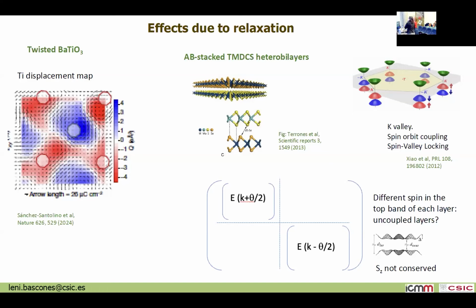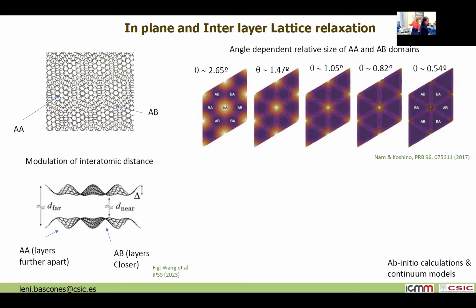G-Dye says, will the interlayer distance change at different twisted angles? I think that the distance probably changes a bit, but it's not extremely different. But the buckling is going to be somewhat different. For example, here, because the AB region becomes very large, you mostly have the distance associated with the AB region, and here you mostly have the distance of the AA region. So it's important, but it's not something huge.